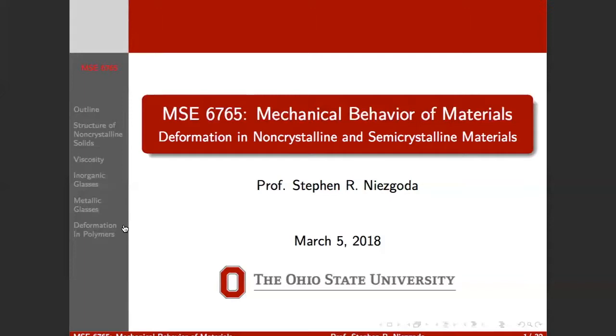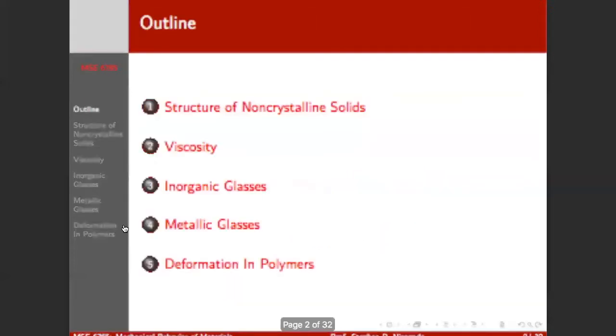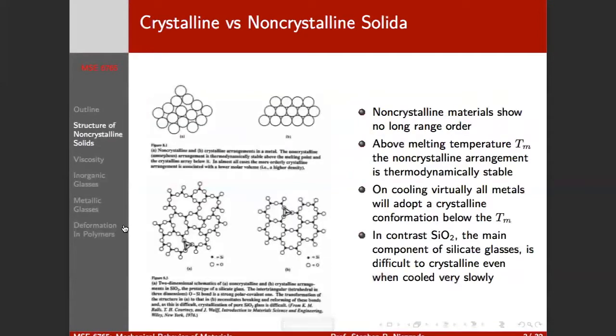But for right now, we're talking about permanent plastic deformation that can, for the most part, be considered independent of strain rate, or it happens at a time that's of the same order as the application of your stress. Not like creep or viscoelastic response, which happens over a very long period of time.